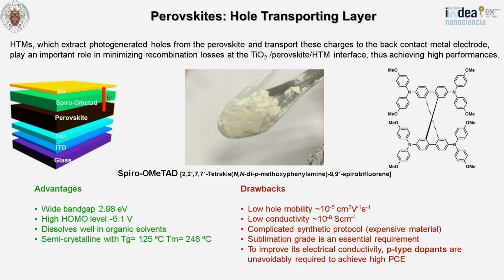The most used material is this one, which is called spiro-OMeTAD. This is the chemical name, for those who like to follow the IUPAC names, okay? There are some advantages. This material has a wide bandgap. I would say 80% of the studies on perovskite have been done with this hole transporting material. It's interesting because of the energy alignment, it dissolves well in organic solvents, and it is semi-crystalline with a glass transition temperature at 125. But there are many important drawbacks.